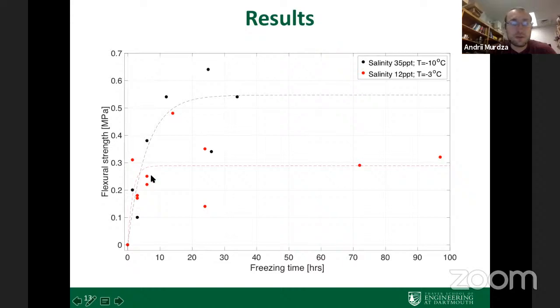From this, you can see that unlike with the freshwater, here with the saline ice, the strength saturates a bit slower. So it takes somewhere from maybe 6 to 15 hours, roughly, to saturate. And after it saturates, it just stays constant.